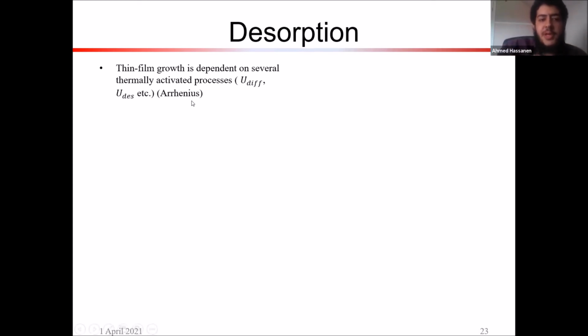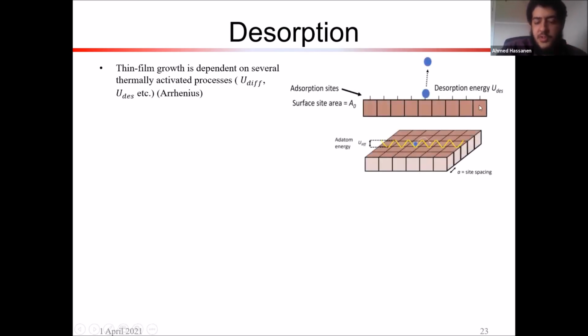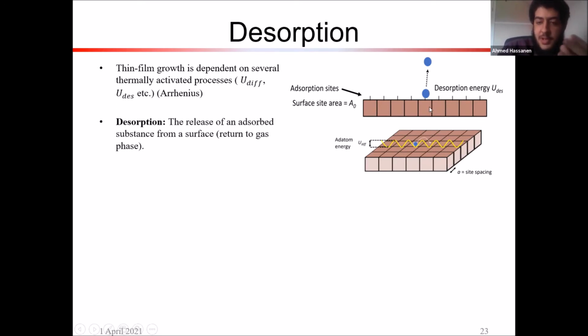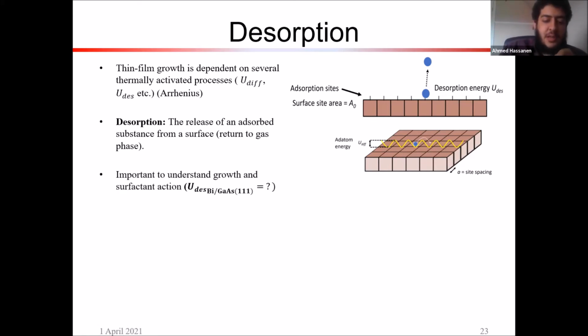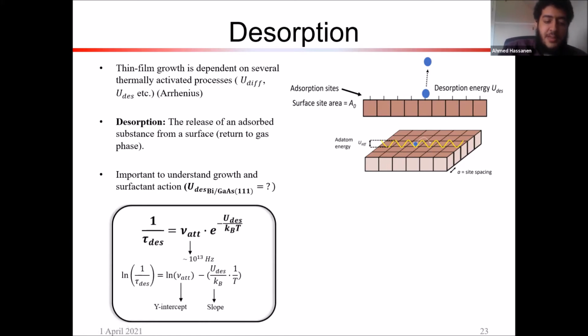And so thin film growth is dependent on several thermally activated processes, like for example, diffusion and desorption. Desorption is just the atom being released into the gas again from the layer. And this is a thermally dependent process. Same with diffusion across the surface. And we can have these energy barriers to translate that into equations. So for growth and surfactant action, it's important to understand the desorption energy of bismuth on gallium arsenide 111.